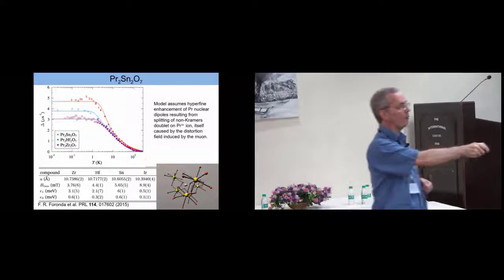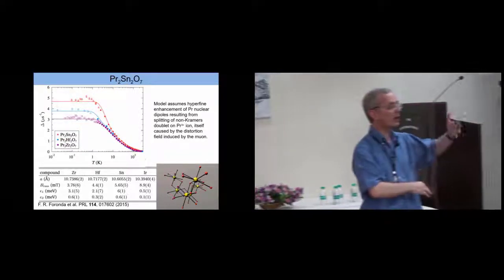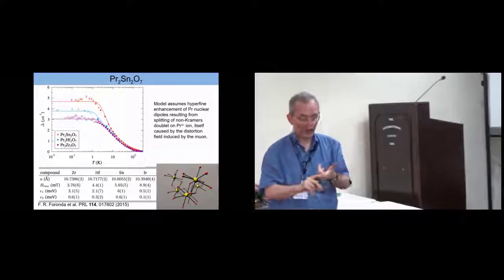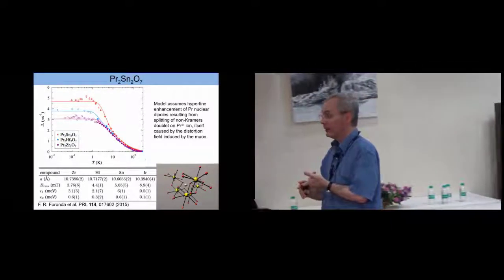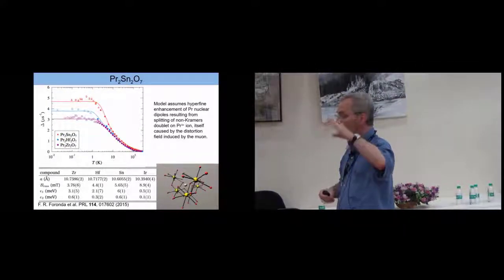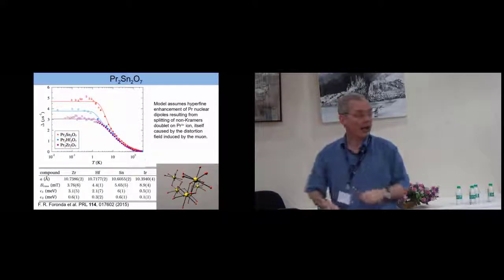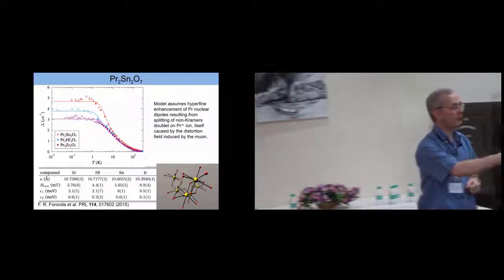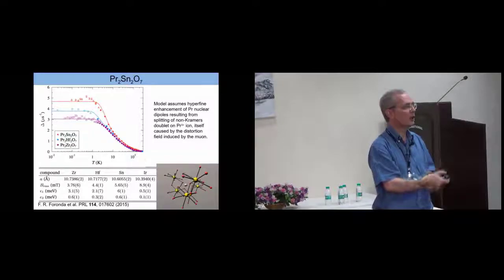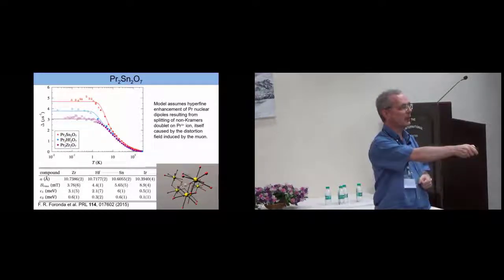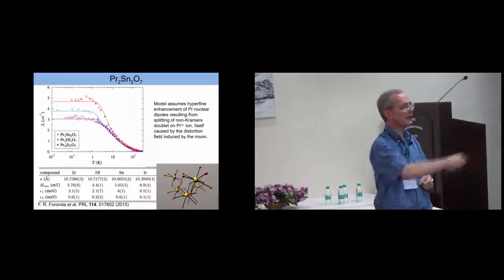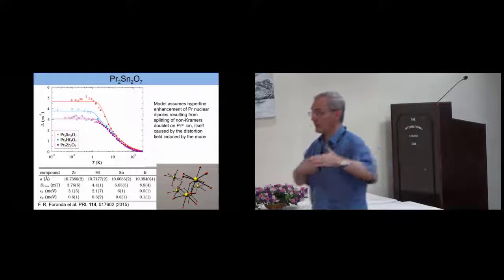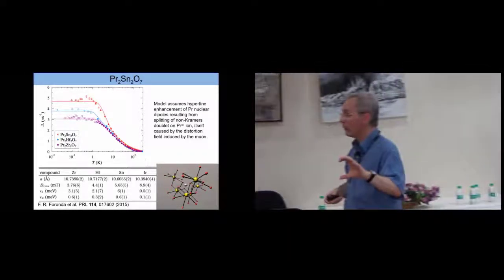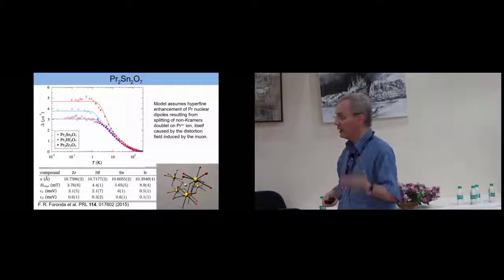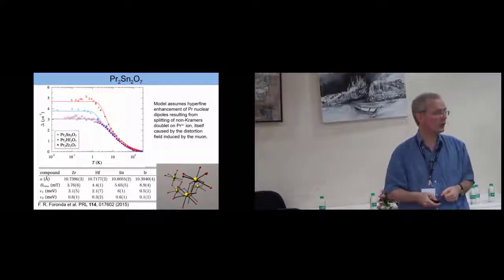There is a theory from hyperfine enhancement that essentially requires having ground state singlets. And then you get hyperfine enhancement of the praseodymium moments. And there is a theory from Bleaney in the 1970s, which we adapted for the muon case, which we can then use to fit these curves. And this gives us an independent estimate of the crystal field splittings, which agree very well with what we've got from our DFT plus mu calculations.